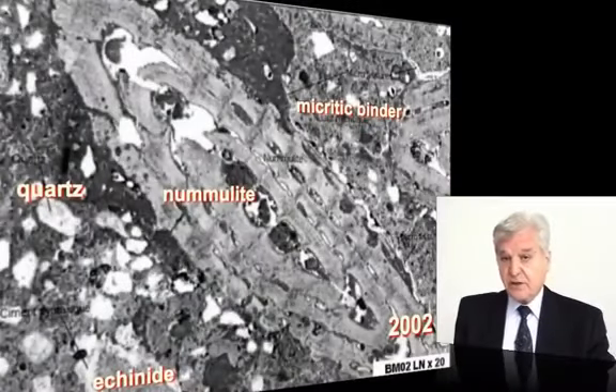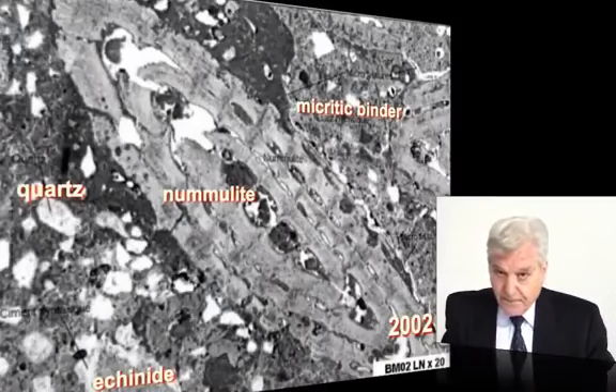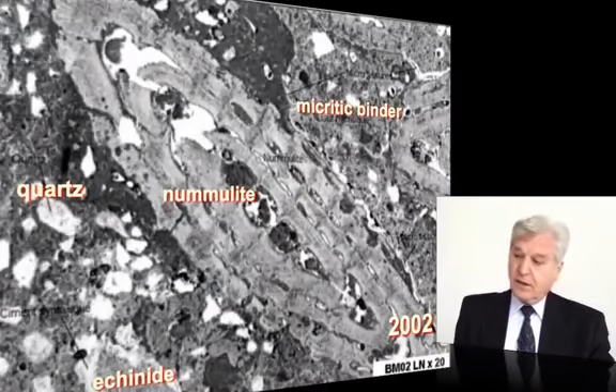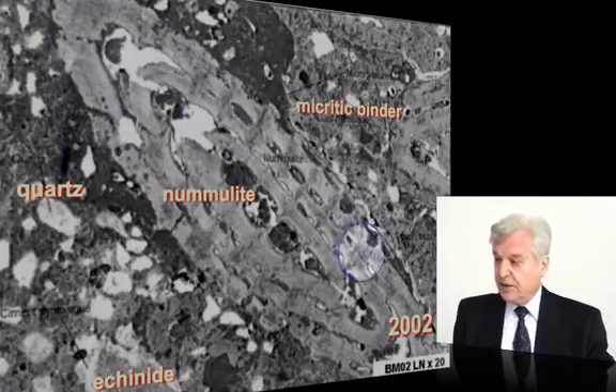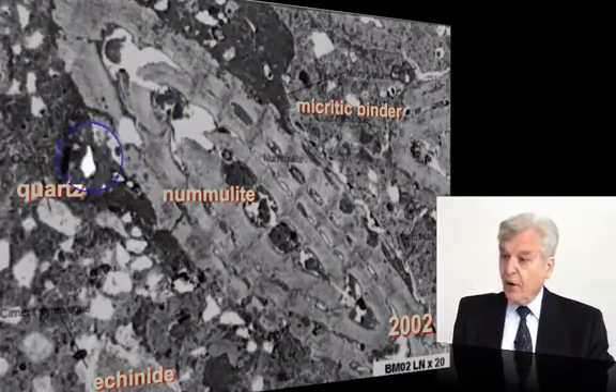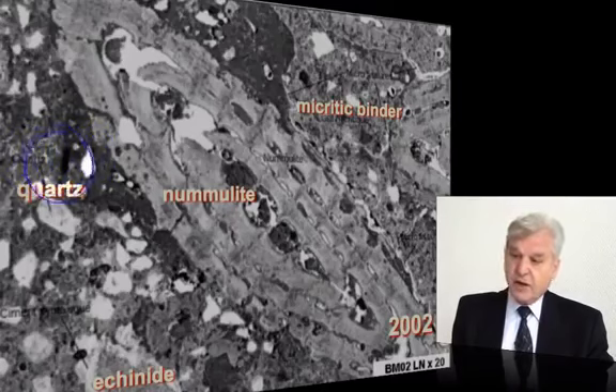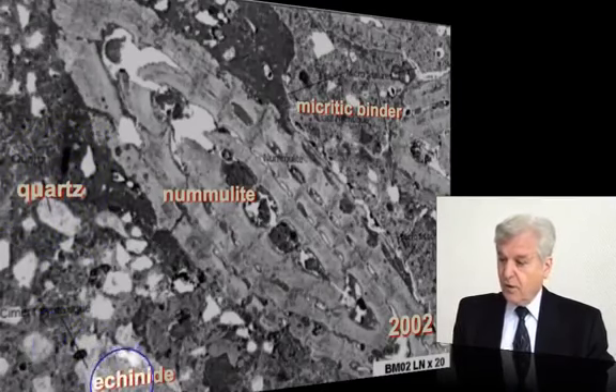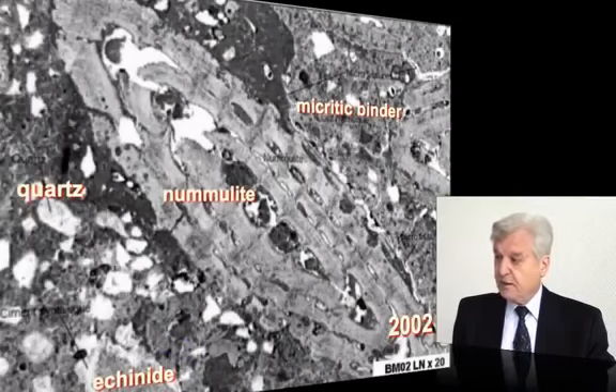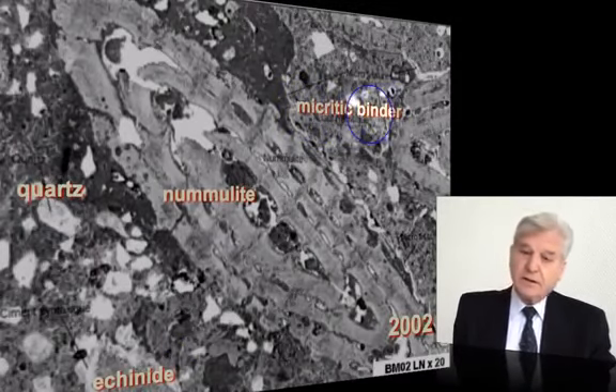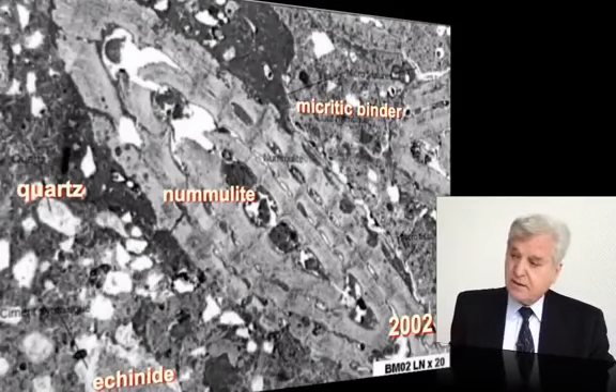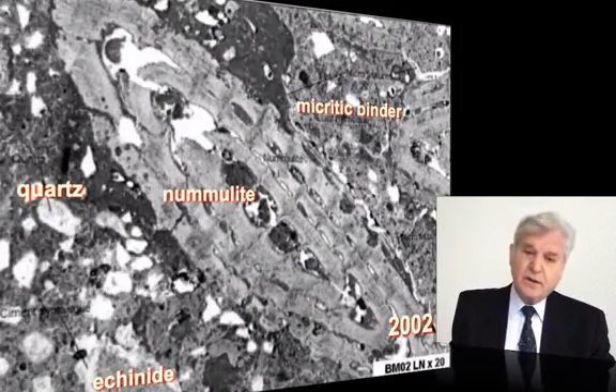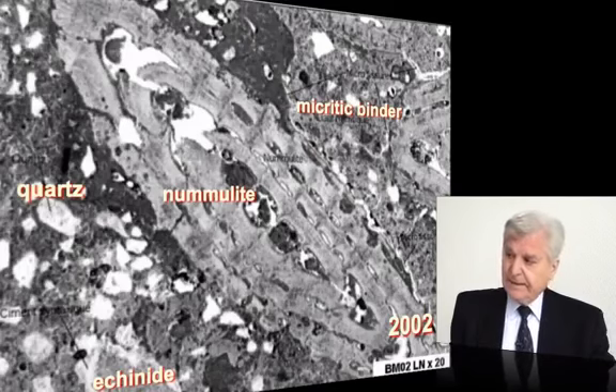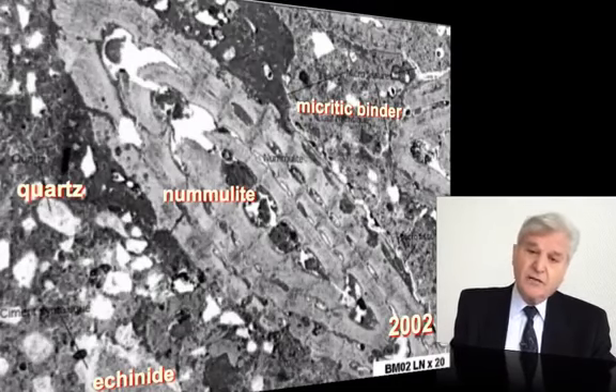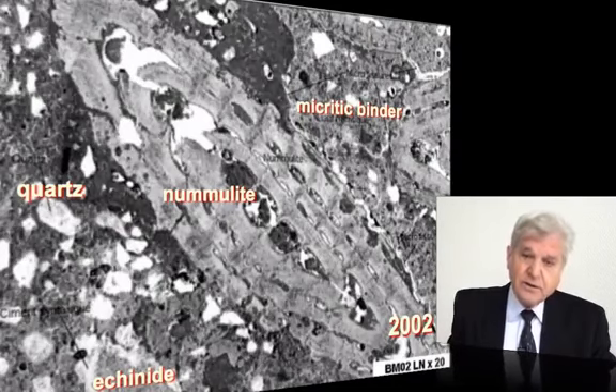This is the thin section of what we gave them. Obviously, you see the big nummulite, then other natural artifacts like the quartz or the echinids, and in between the micritic binder. The micritic binder is a binder that is made of very small particles of calcite, and they claimed that this was the thin section of a natural nummulitic limestone.